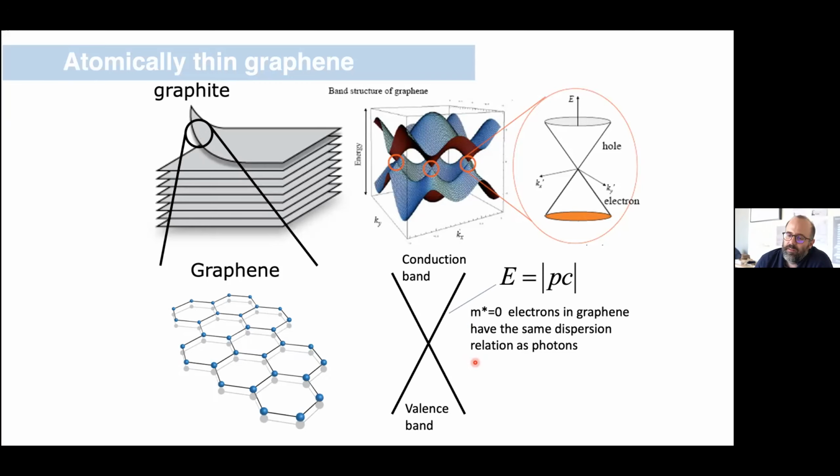And you might already suggest that this band structure puts it slightly outside the classes of materials that I discussed a moment ago. It's not really an insulator or a semiconductor because there's no true gap in the system. And it's not really a metal, you might say, because the Fermi energy tends to exist right at this crossing point, where the density of states, theoretically anyways, is zero. So for that reason, graphene is sometimes called a zero gap semi-metal or some version of that. So it's kind of its own thing.